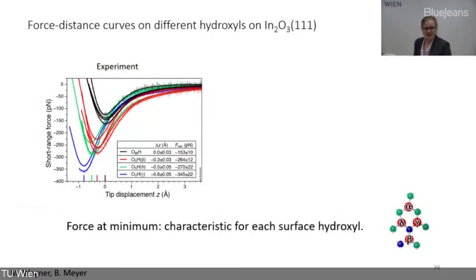These are the force-distance curves where the tip goes in and comes out again, measuring the short-range force between the very end of the tip and the surface. You can see 4 curves - black, red, green, and blue - representing the 4 different types, each on a different surface hydroxyl. It's a very characteristic feature we observe.